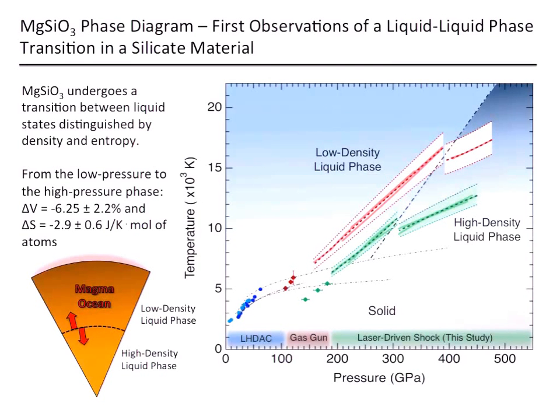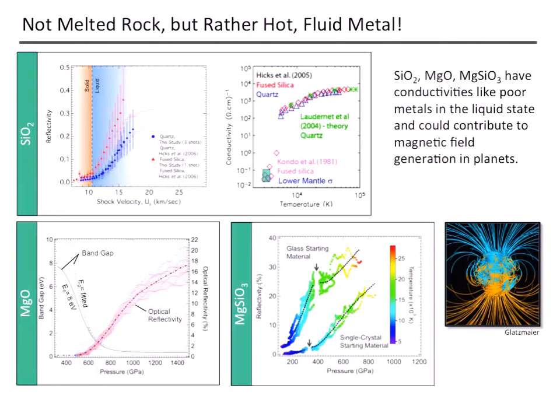We also measure the reflectivities of the shock fronts, and this gives us information about conductivities, electrical DC conductivities and thermal conductivities. And what we find out is that all of these minerals, quartz, MgO, and MgSiO3, all start behaving like poor metals in the liquid state, which has implications for the magnetic fields of extrasolar planets.